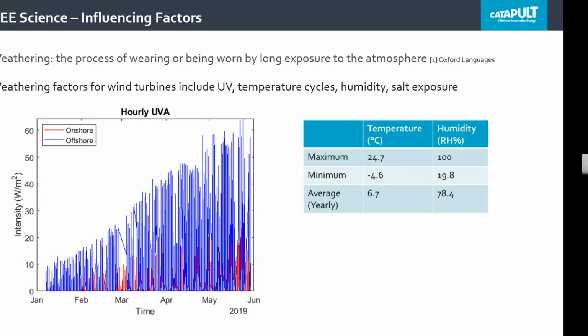offshore. So although we're talking about degradation through rain impacts, there's obviously going to be degradation through UVA and UVB weathering impact that also needs to be taken into account in future solutions. Just to note in terms of temperatures and humidities offshore, the maximum measured temperature that we've recorded is 24.7 degrees C, and the maximum humidity is 100%. The minimum temperature is minus 4.6, with a minimum humidity of 19.8, and the average yearly value shows that it's quite cold offshore, with a high humidity environment in general.